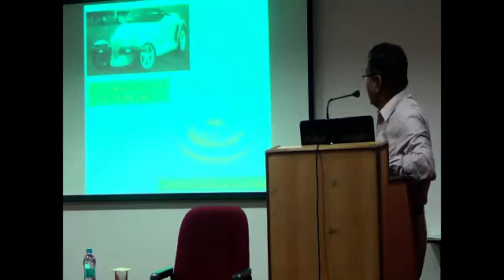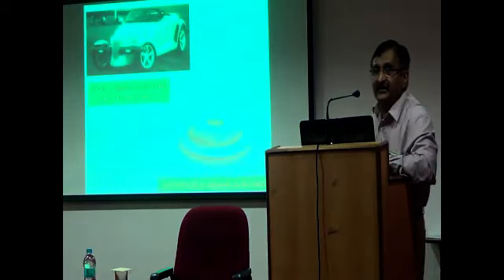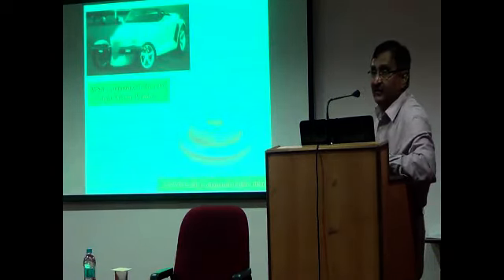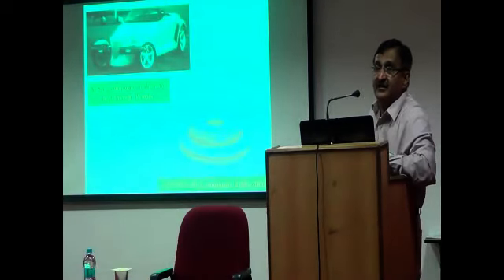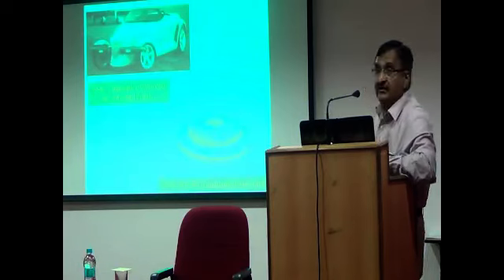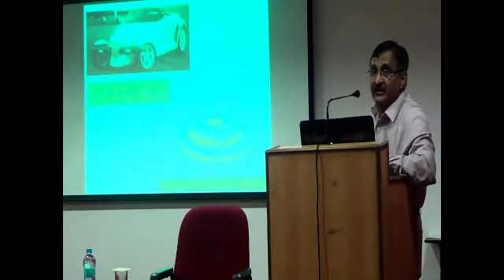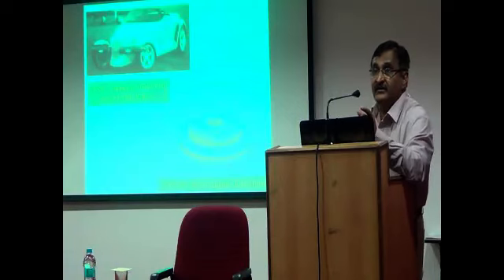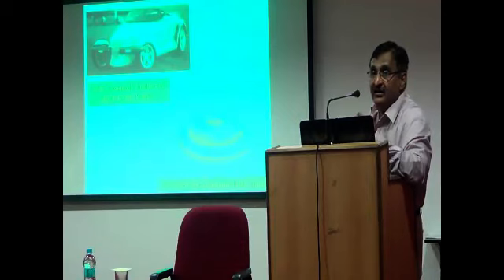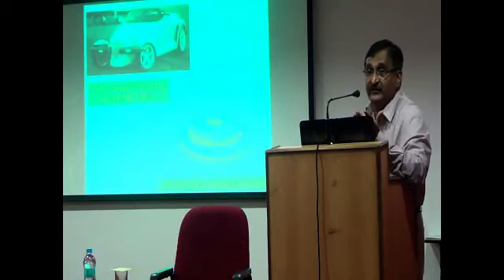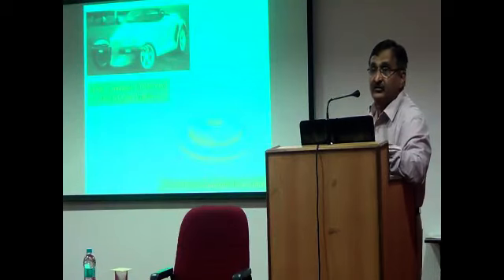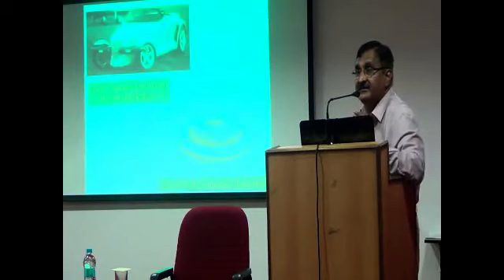This is the kind of disc that is used in a car. These were generally made of cast iron, weighing something like 21 kilograms. Instead of cast iron, if you use an aluminum composite, that's one third the density. Then you can reduce the weight of the automobile, so you increase its fuel efficiency and reduce its emissions. Many other environmental benefits, and noise pollution can reduce considerably. But you have to establish that the composite made with silicon carbide has the same level of wear resistance as cast iron.